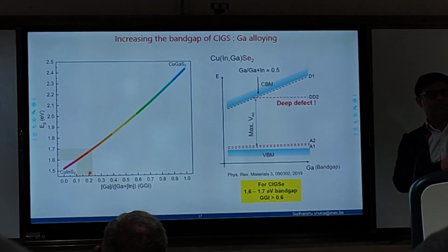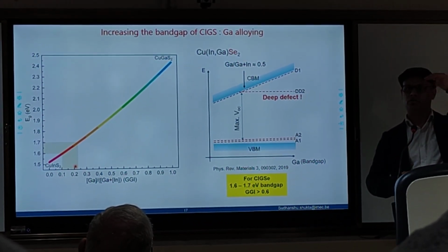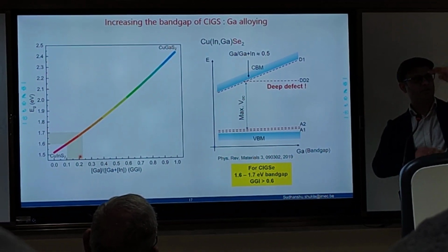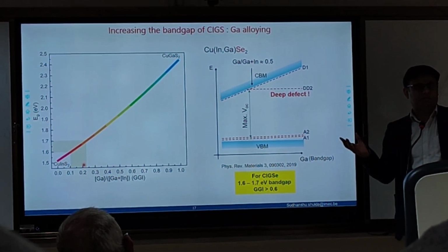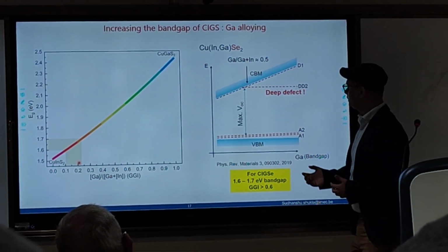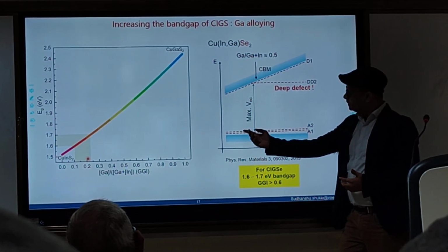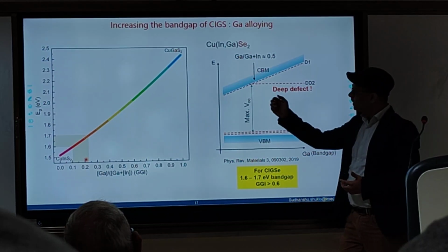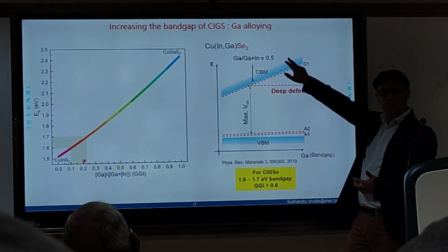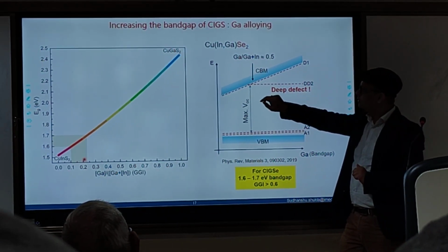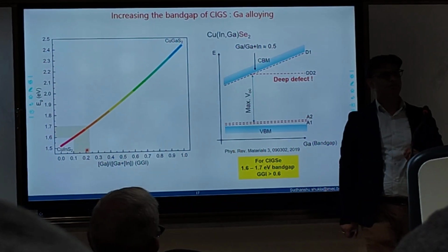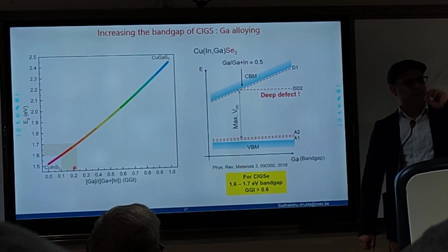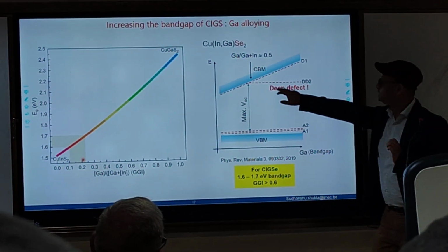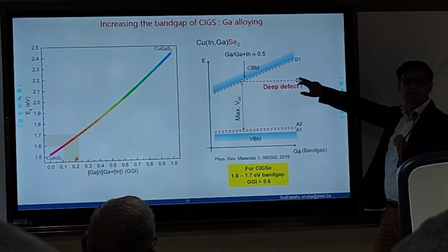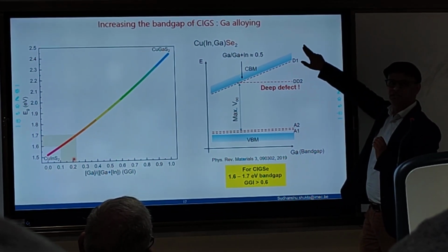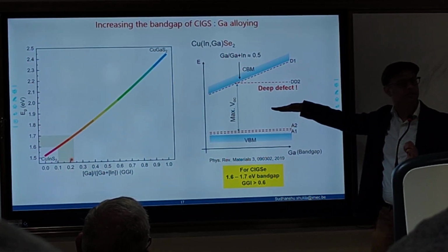But what happens when the band gap changes? Either the conduction band goes up, or the valence band goes down, or both can change. So this is something we don't know, so experimentally we need to know that. So for example, this is the valence band maximum, and then your conduction band starts increasing because you are putting more and more gallium. Some of the shallow defects, meaning the carriers that contribute to the current, some of these defects actually become deep because the conduction band keeps on increasing, but the deep defect does not move when the bands move.